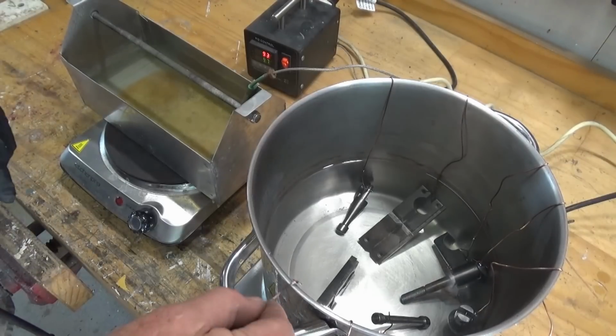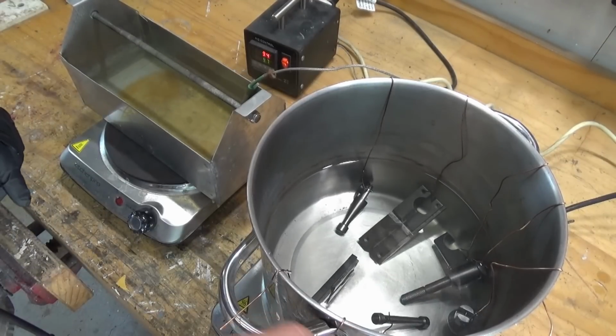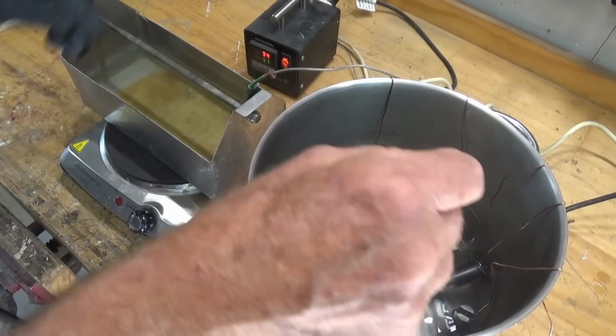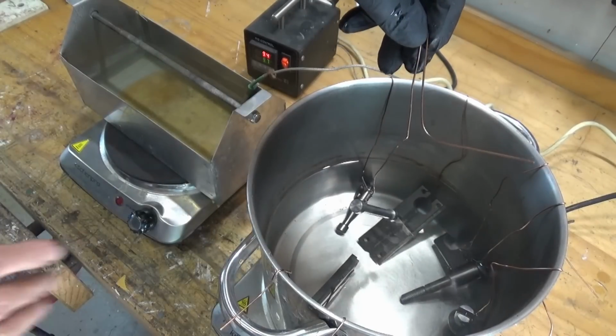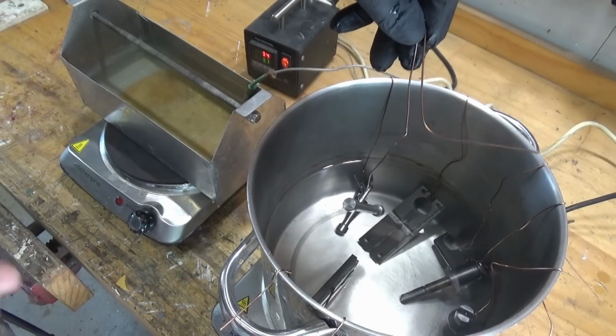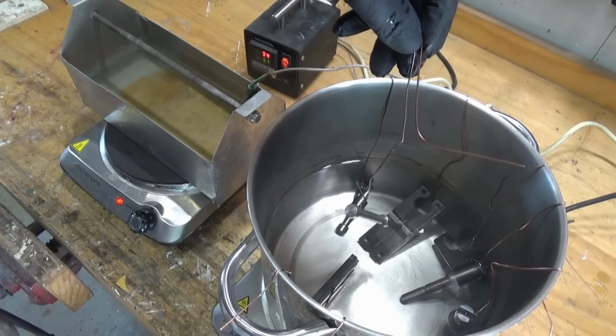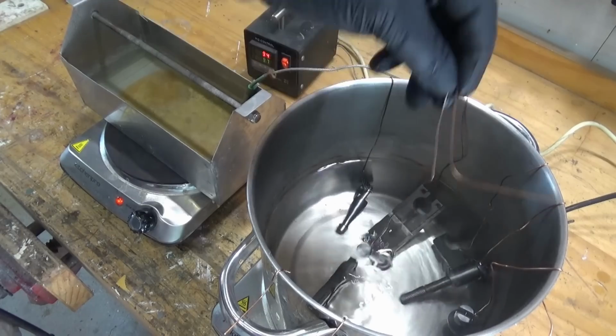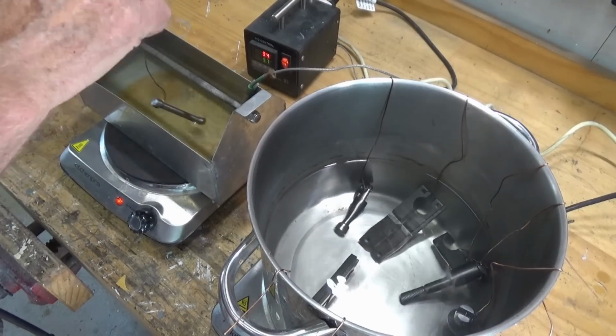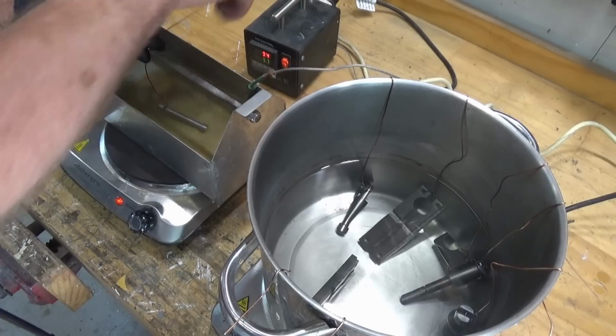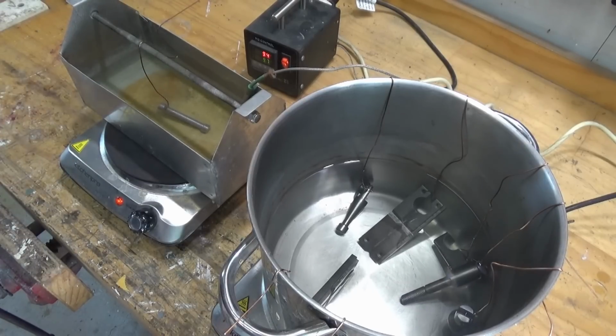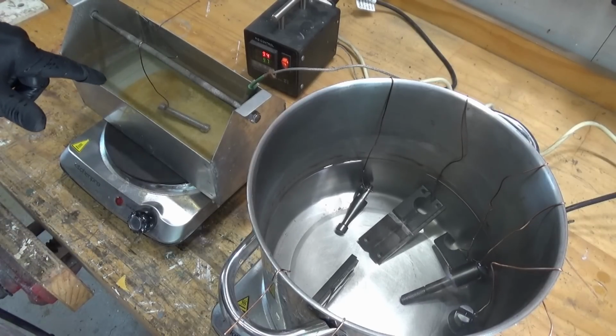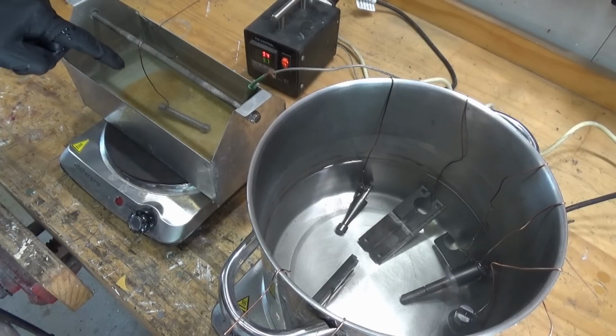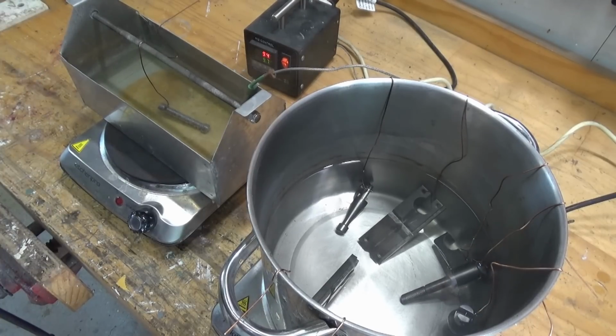Okay, 1 minute's up, so these are going to come out now and they go straight into the Parker phosphate solution. It's heated to around about 95 degrees centigrade. You don't want it boiling, it just evaporates off all the water in the solution. Now, if everything's happening correctly, you should see a stream of bubbles coming off that part immediately, and then we leave that in there for about 15 minutes.